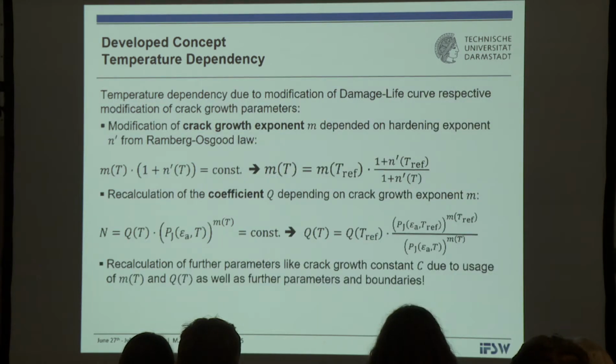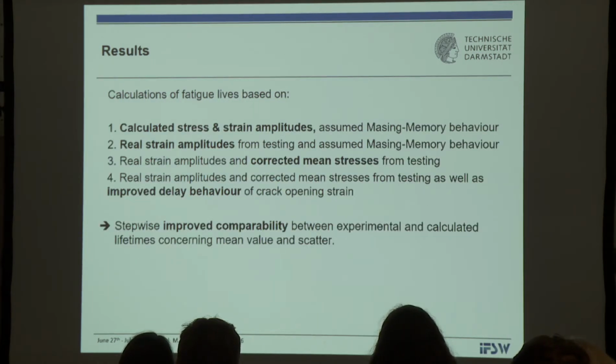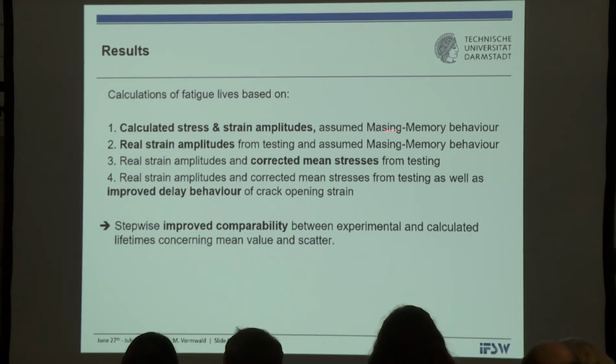So now this is the equational stuff. We performed a lot of calculations. We started with calculated stress-strain amplitudes using Masing memory behavior, conventional local strain approach. I will not show these results. They are as bad as they have been 35 years ago. Then we took the real strain amplitudes from our test and assumed Masing. Accuracy is a bit better, but not reliable. Real strain amplitudes and corrected mean stresses. You remember that we have put our amplitudes to the upper reversal point and the lower reversal point. We are punished with mean stress relaxation effects.